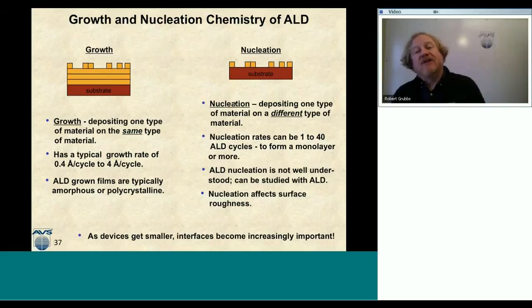One implication of nucleation is that the more nucleation cycles it takes to nucleate a film, the rougher the film is going to be. So if you really try to get these very smooth films, you'd like things to nucleate within 1 or 2 ALD cycles, and then your film will be very, very smooth. So as these devices in our day and age get smaller and smaller, interfaces are going to become increasingly important, and it's going to be increasingly important to really understand the dynamics that happen and the bonding that is occurring at the nucleation phase of the thin film growth.